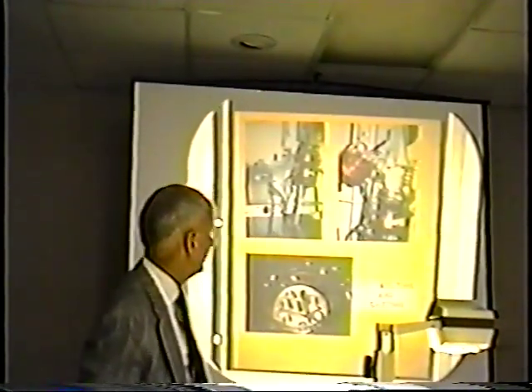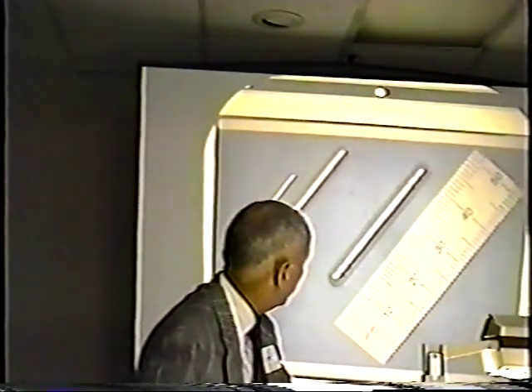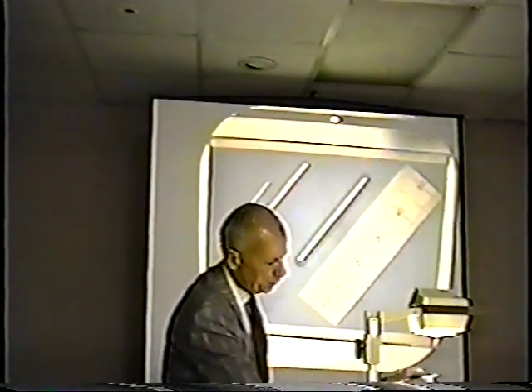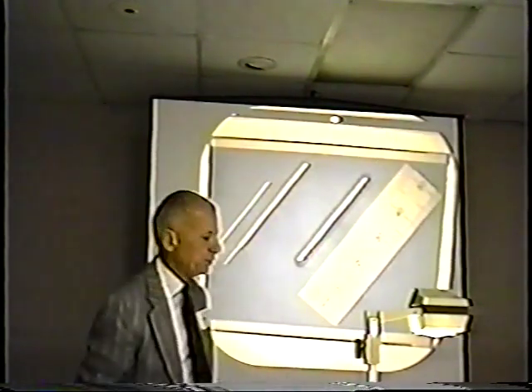We have, beside my division and the chemistry division, an entire materials division. They're well equipped, and they were able to bring to bear some good machinery already in place in order to make electrodes for the experiments, the kind of electrodes that were manufactured within the lab. This is an example here, about 4 millimeter diameter, and you see a few centimeters long, and it was machined without oil. Great care was taken to keep it clean. You have the grooves here for the 4-point resistivity measurements. We did the spot welding with palladium contacts to avoid contamination. It was a very, very careful piece of work.